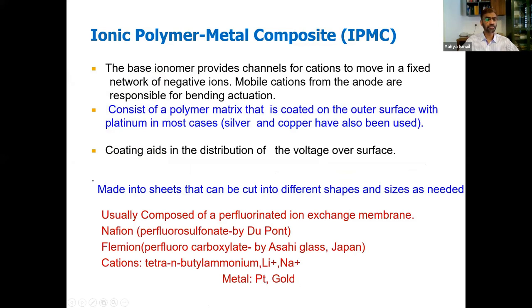Then ionic polymer metal composite. You have a base ionomer, base polymer, that provides the channels for cations to move in a fixed network of negative ions. Then these mobile cations from the anode are responsible for bending actuation. Not only bending, the video that I've shown shows a bending actuation, but at the same time, they can also produce linear actuation. But bending actuation in this case is more visible in IPMC-based material.